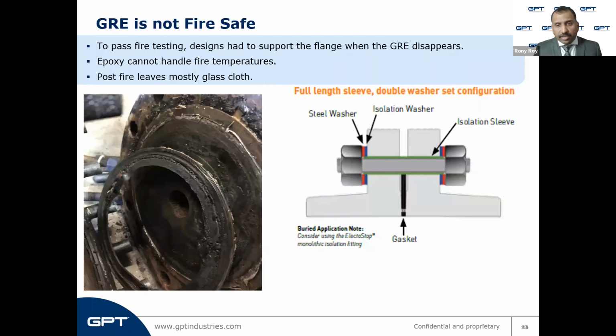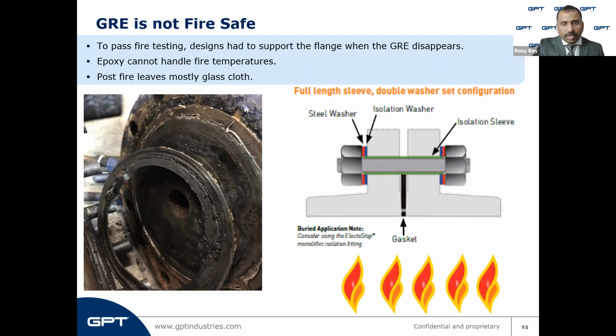So when you subject a standard flange isolation gasket kit to fire, you can see here, it tends to have some failures. The gasket itself with its plastic laminates fails after a certain degree Celsius. So G11 would fail after 200 degrees Celsius, G10 would fail after 150 degrees Celsius, and so it leads to a fluid leak path. The other failure components are the isolation sleeve, which is also made from G10 or G11, and the isolation washers, which are also made from G10 or G11.